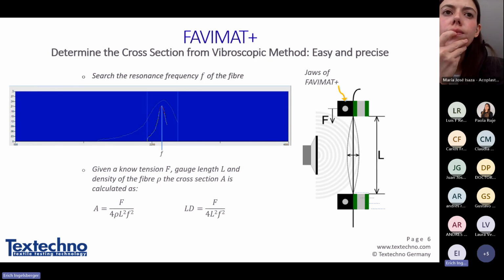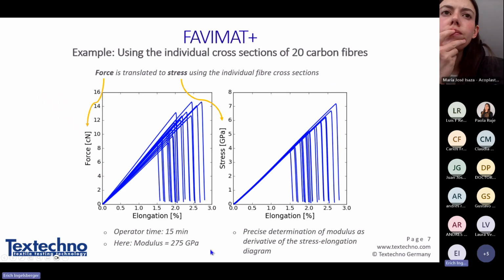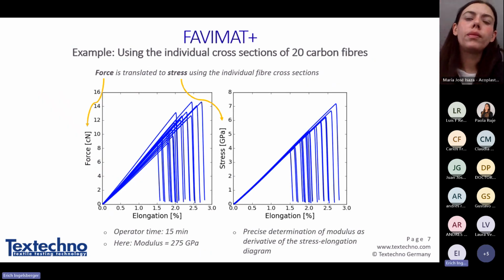So this vibroscopic test method can be used to measure the cross section of the fiber, which is important. We do this on every individual fiber - fiber by fiber, we first measure the diameter or cross section and then the tensile properties.